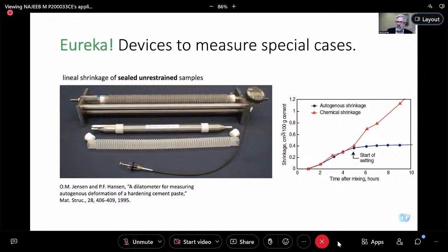And one of the primary results that we see again and again now in literature is this autogenous shrinkage compared with chemical shrinkage. And we see the divergence when we start to get to that point where the skeleton is now stiffening and the autogenous shrinkage is no longer able to shrink because it's restrained by its own volume, whereas the chemical shrinkage is continuing due to hydration. And this area where you diverge is stress, where the body of the material is resisting these stresses that are caused by shrinkage, and cracking can occur.